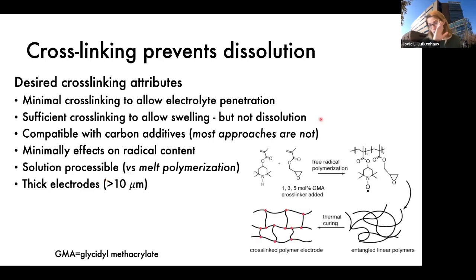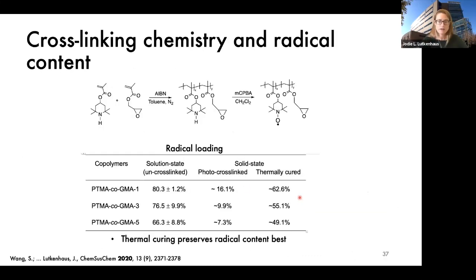In this case, we're still making PTMA, but we're adding a little bit of glycidyl methacrylate as a cross-linker. We looked at very low concentrations of 1, 3, and 5 mole percent of GMA, or glycidyl methacrylate. We compared photo cross-linking and thermal curing for these different compositions. The main message I want to get across on this slide is that photo cross-linking is a bad idea. There's something about the light that is either damaging the TEMPO radical or causing some side reaction, so that photo cross-linking causes you to lose a great deal of radical activity. However, if we thermally cure above the glass transition of the polymer, then we can still maintain a lot of the radical content that we were looking for. We lose some, but it's much better than photo cross-linking.